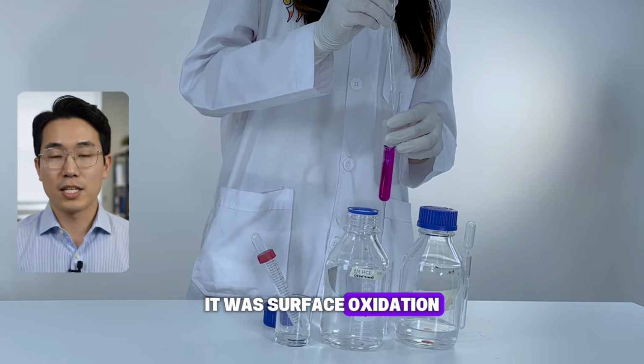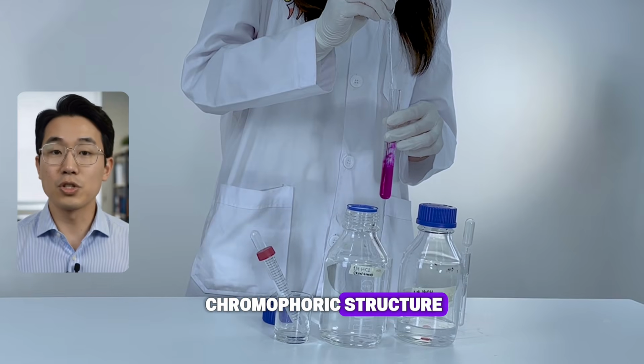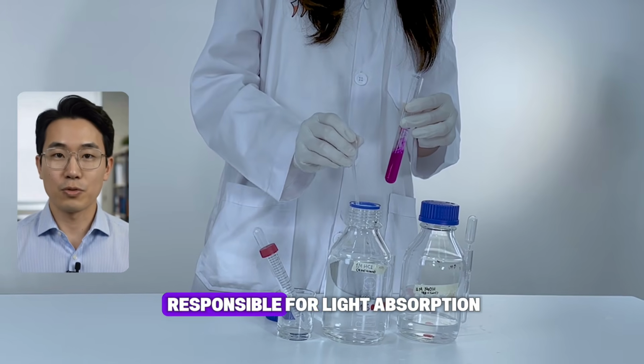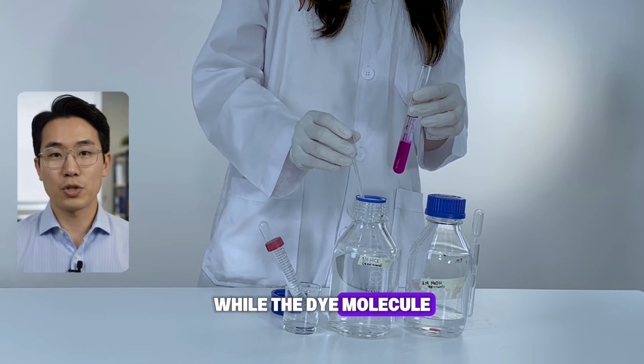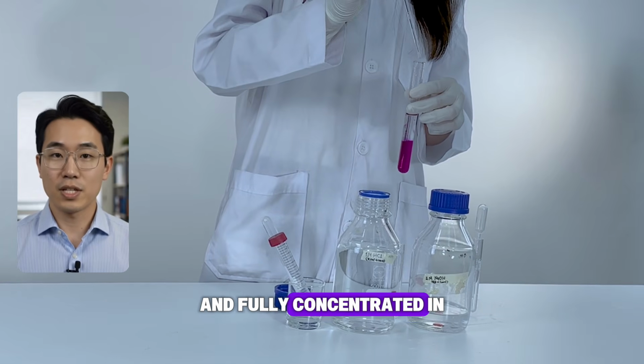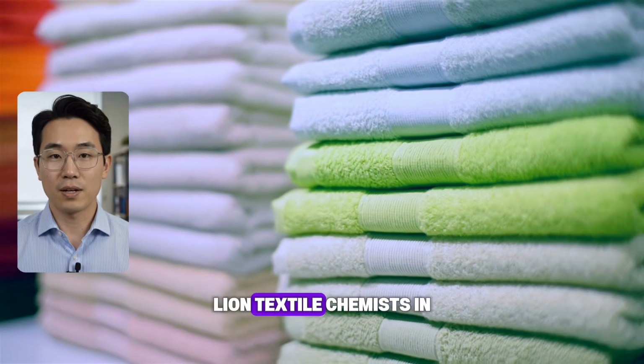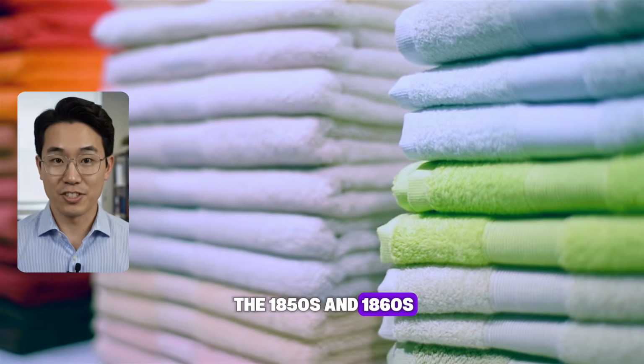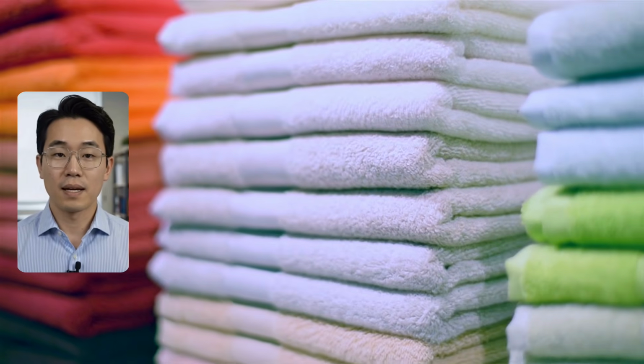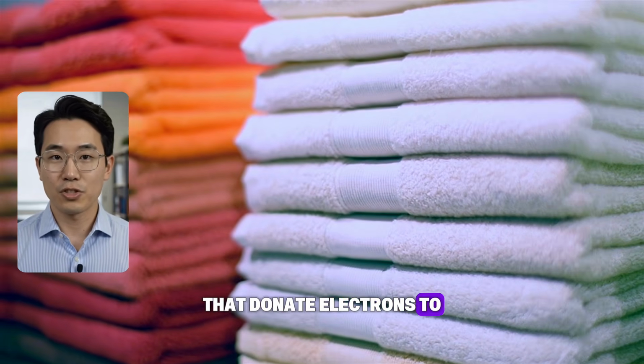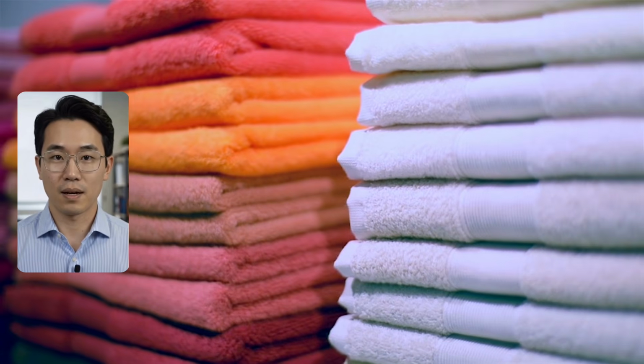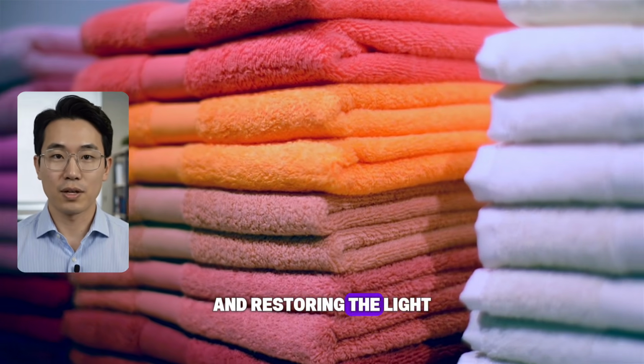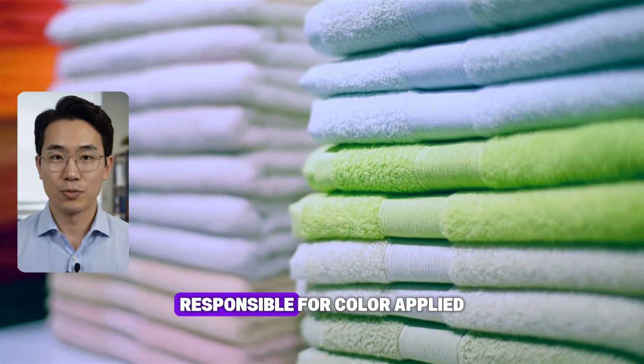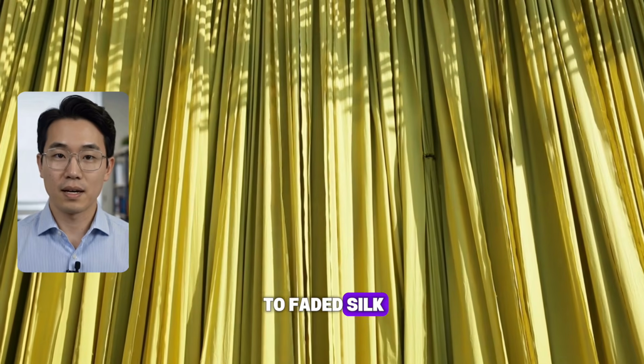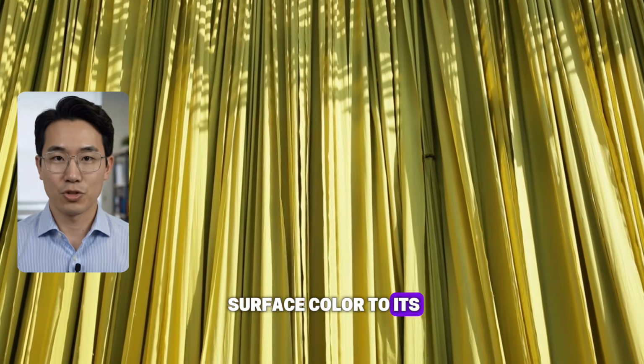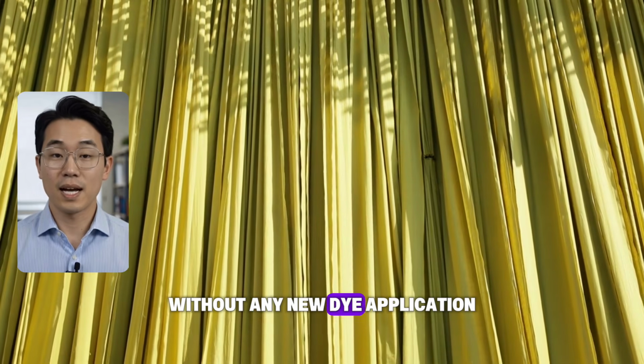It was surface oxidation of the dye molecule's chromophoric structure, the specific chemical bonds responsible for light absorption, while the dye molecule itself remained intact and fully concentrated in the fiber. Lyon textile chemists in the 1850s and 1860s developed reducing agent treatments, chemical compounds that donate electrons to oxidized chromophoric structures, reversing the oxidation and restoring the light-absorbing bond configuration responsible for color. Applied to faded silk, these treatments restored the surface color to its original saturation without any new dye application.